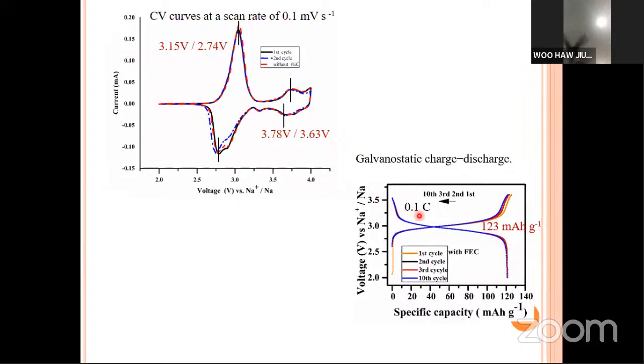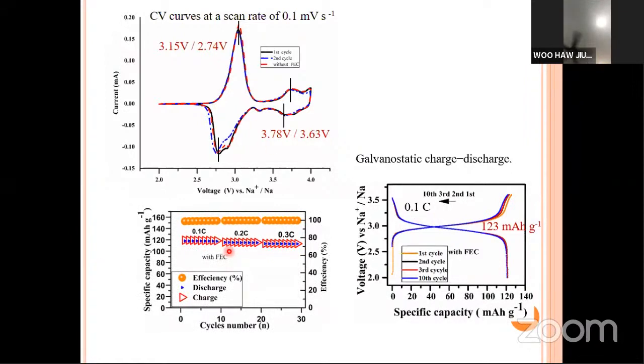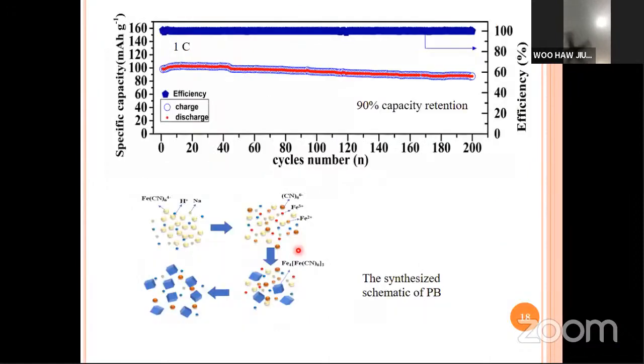However, this is at a low C rate, okay? Then we also tested higher C rates, slowly increasing to 0.2 C and to 0.3 C. It works with quite high Coulombic efficiency, close to 100%, at above 100 milliampere hour per gram. Then we ran 1 C, and after 200 cycles, it retained 90% of the capacity. We couldn't run a C rate higher than 1 C because the product is no longer stable at higher C rates. So this is the schematic diagram of our synthesis of Prussian blue.